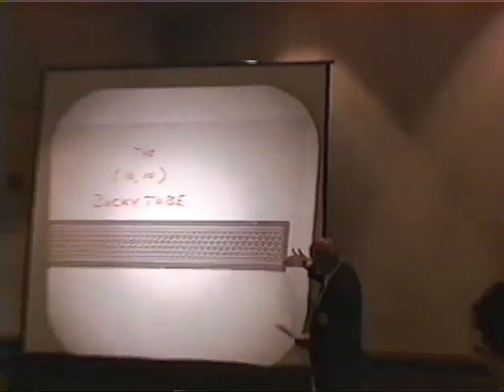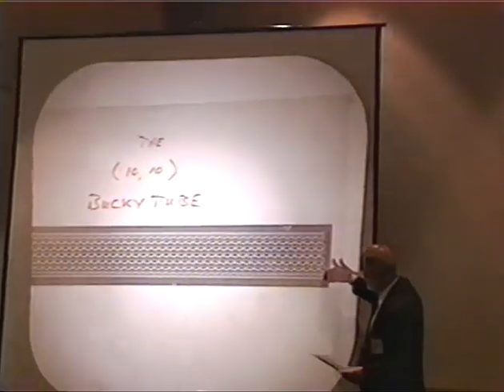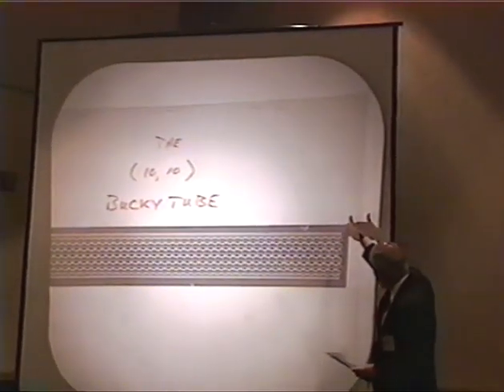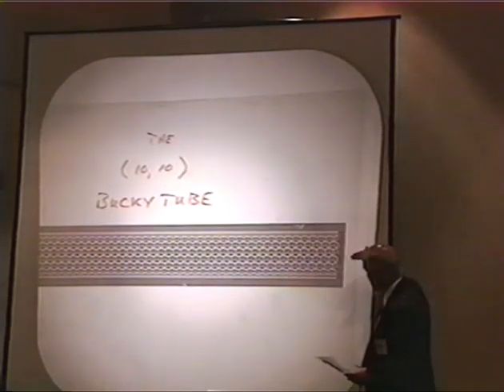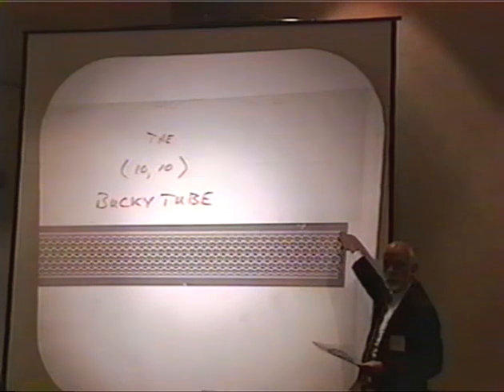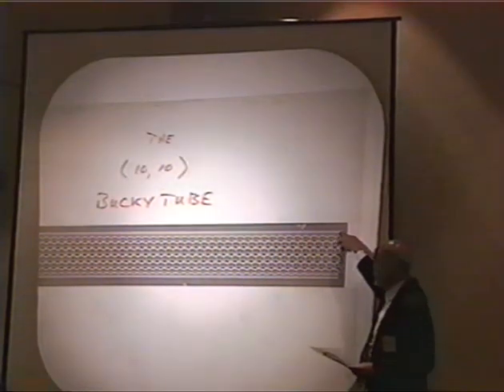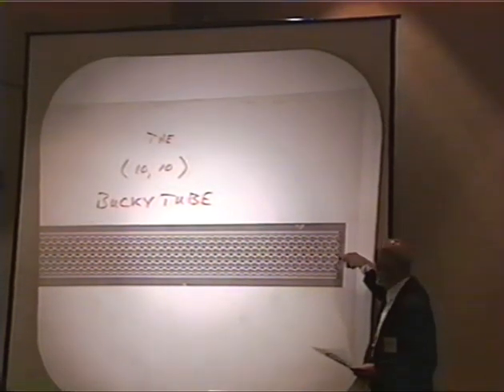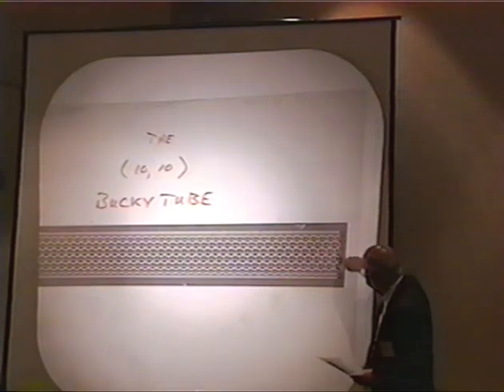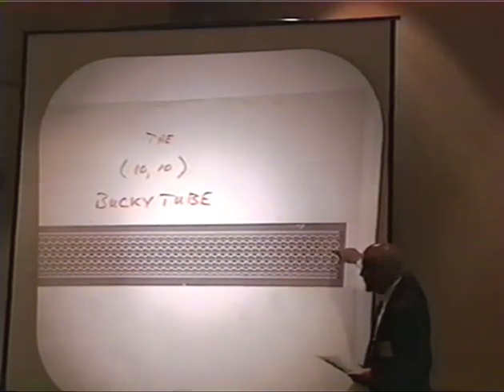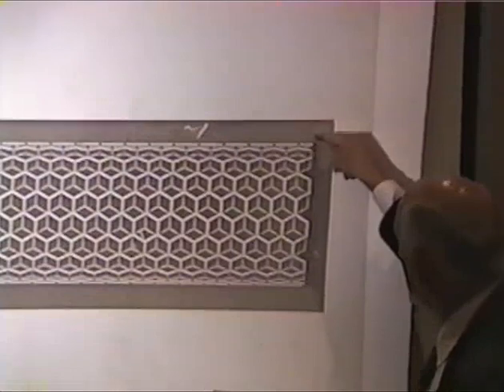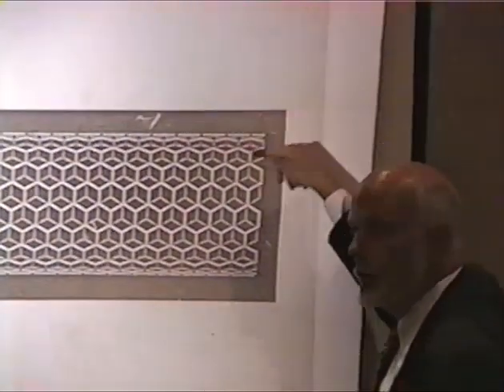If you look at the end of this tube, if you cut it open with a cut that's precisely perpendicular to the tube axis, you notice that only the sides of the hexagons are exposed. This is generally called the armchair edge. I guess that's the arm of the armchair, and this is the seat of the armchair, and so there's enough place for 10 people to sit on this.